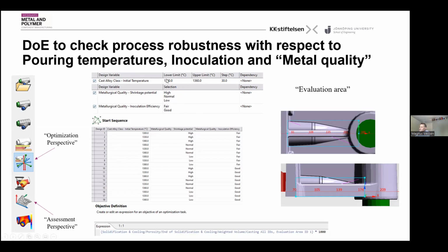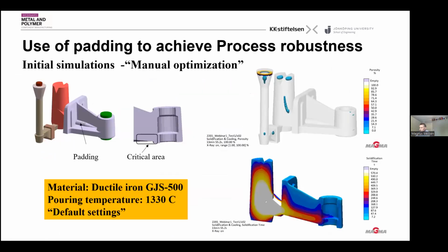So then you have 3 levels of the temperature, 3 levels of the metallurgical quality, shrinkage potential, and 2 levels of the inoculation. So now you have directly 3 times 3 times 2. That means 18 possible designs. Of course, this is done with, say, 2 minutes extra work. Just go in here and select your parameters which are varying, and then create your start sequence. And in this case, it's a full factorial design. You can also do reduced factorials and fractional factorials, but in this case, I will only discuss full factorial designs. And of course, then you have to think about what your objectives are, what you would like to achieve. So in this case, we know that this was the critical area.